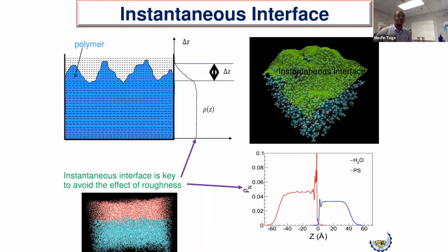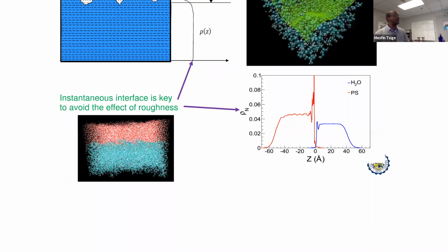The liquid-liquid community, however, have been using what's known as the instantaneous interface approach. So what they have said is, instead of simply looking at a rigid coordinate system, take your surface of reference to be this surface instead of a plane. So that surface takes into account the roughness, and we look at the distribution of molecules with respect to this surface rather than with respect to a plane. When we do that, we actually start to see some of the molecular details. We observe ordering at the surface. That is what has been expected, but we were not able to see it first with the slab approach.